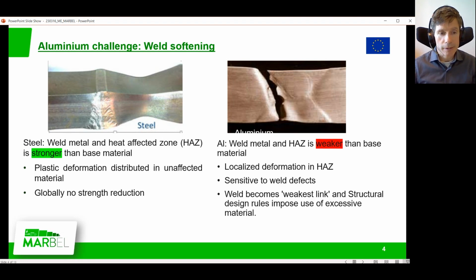In aluminium, on the other side, in the alloys that are heat treated by solution hardening and precipitation hardening, which are the ones we are normally using, the weld metal and the heat affected zone are weaker than the original base metal. So in straining or in any deformation, the tension is localized close to the weld, and there it breaks rather easily. And it is also very sensitive to small defects in the weld. So this is the main challenge of aluminium in design. And this then creates a system where you have to redesign or opt to make the geometry much thicker than it otherwise should have been.